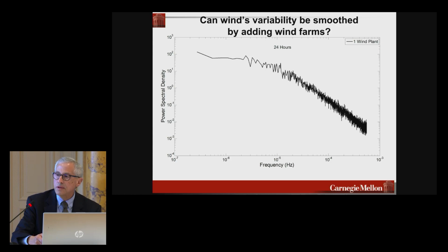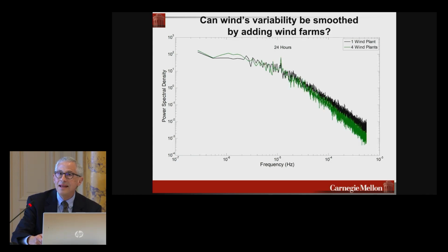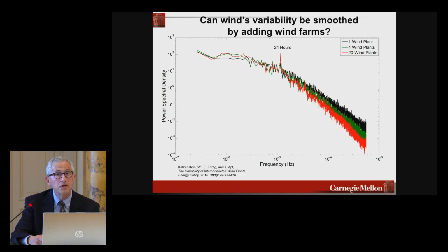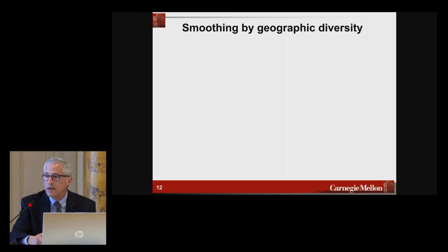Does it smooth the fluctuations out? And the answer comes quickly. Here's 4 plants together, and we see that the high frequencies are somewhat damped, but not much change in the very strong low frequencies. Here's all 20 of the largest wind plants added together, and you get about an order of magnitude of smoothing at the highest frequencies and essentially none at the lowest frequencies. At periods like an hour, you actually damp out about 95% of all of the fluctuations, but at 12 hours, it's only half of the fluctuations, even adding all of the wind plants together. So I'll show you that quantitatively.